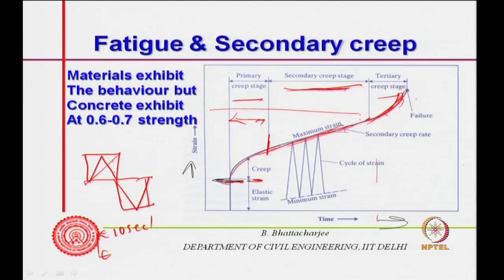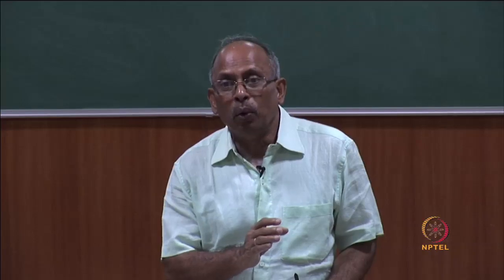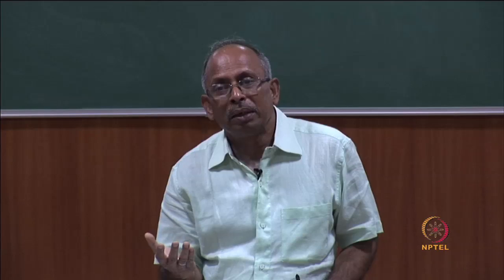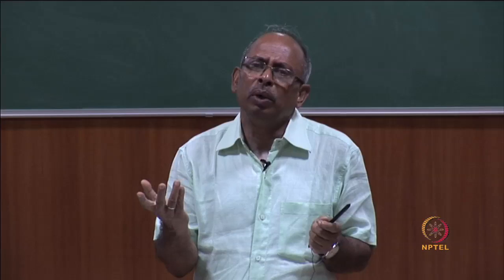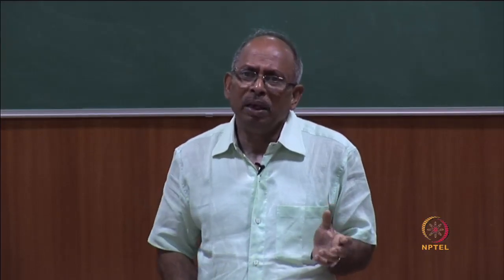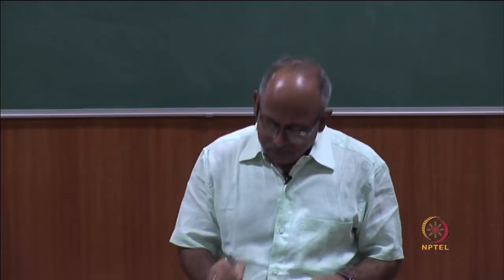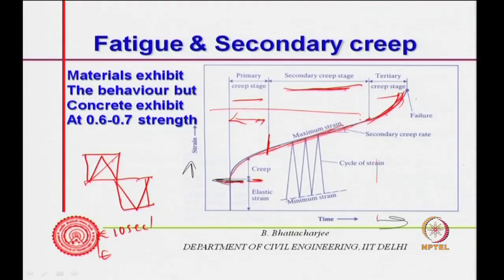So, fatigue is a case where reversal of stresses occurs at a very fast rate, cycle time is low. But if the cycle time is infinity, that is a very long time to complete the cycle, practically my load is constant. So, that is actually sustained loading. So, there is a relationship between sustained loading and fatigue. When I have reversal of stresses, it goes to minimum, but the load is still sustained, it has not gone away. So, when I come back, I do not come back to this point again, but I come back somewhere above, because load has been sustained for a certain period of time.